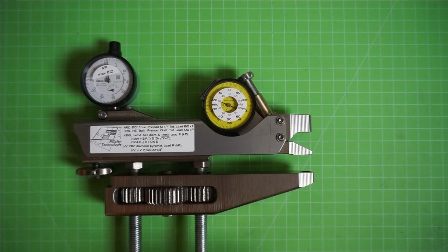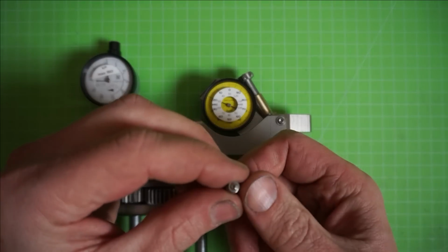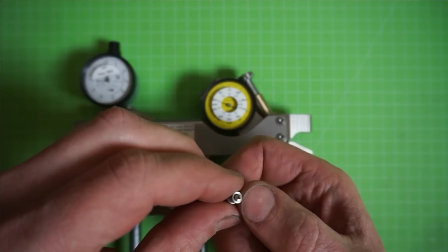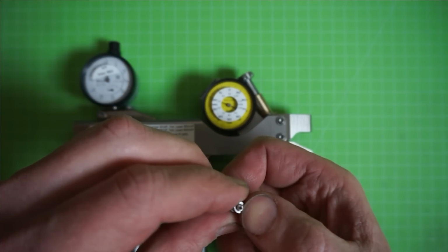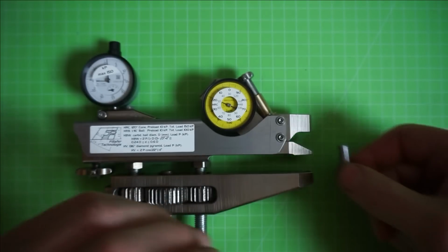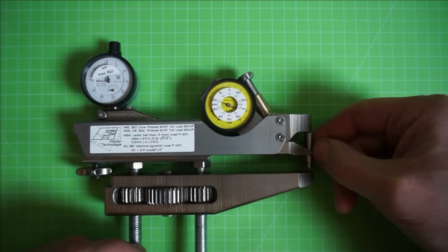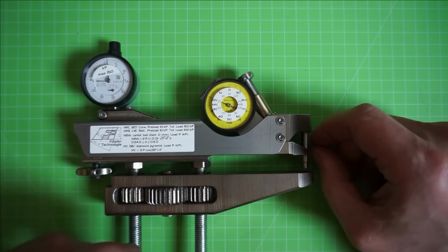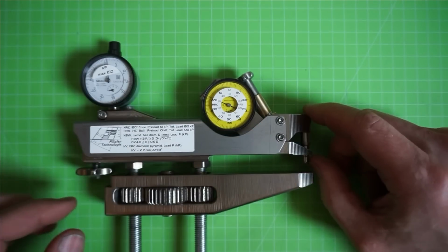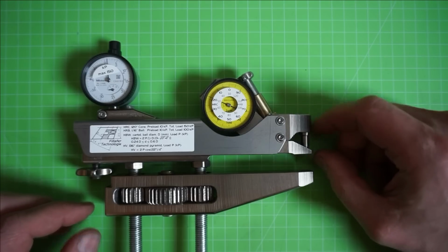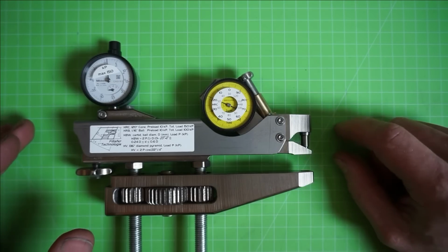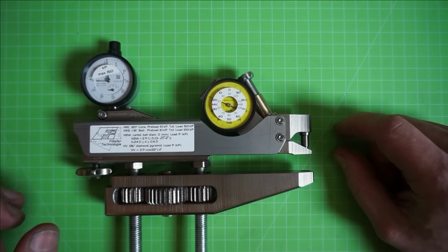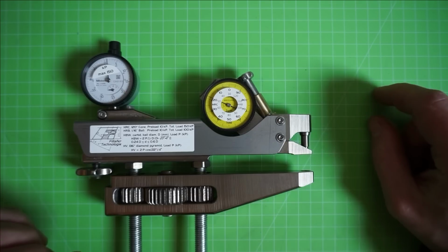Vickers uses an indenter that is shaped like a pyramid. There is a diamond tipped pyramid here on the indenter. And the nice thing about this pyramid shape is that the indentation is a square. No matter how deep it sinks, it's always a square. The Brinell test is different, it uses a ball, and the problem with that in comparison to Vickers is the deeper it sinks, the sharper are the edges.